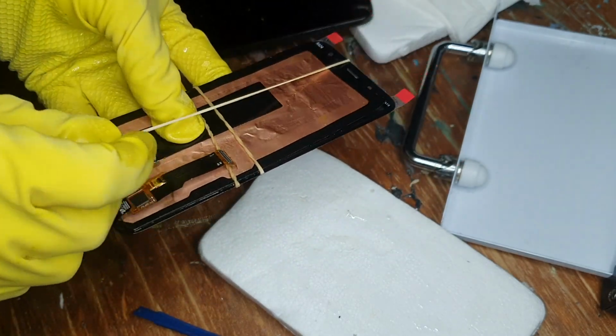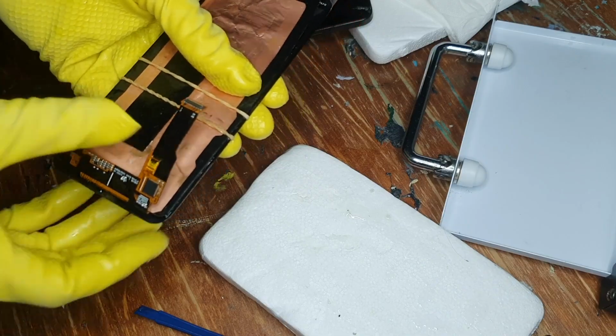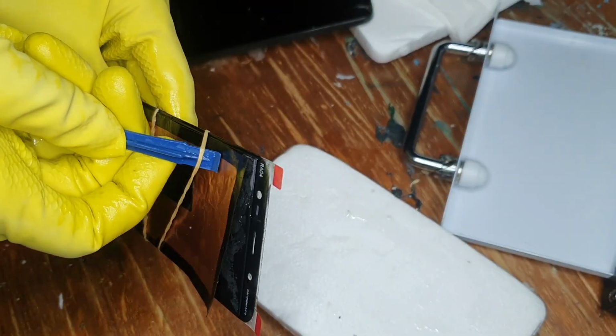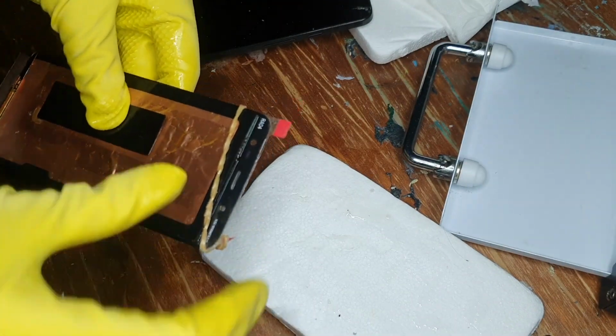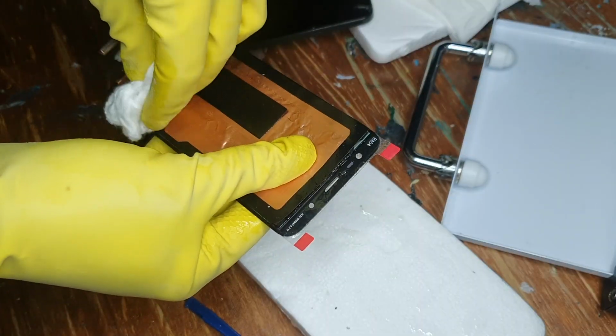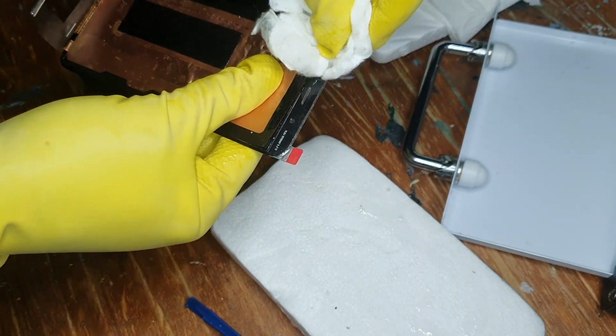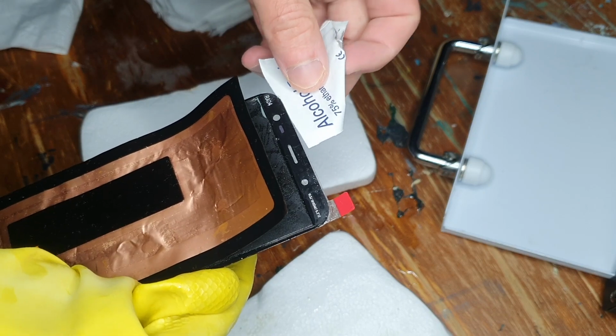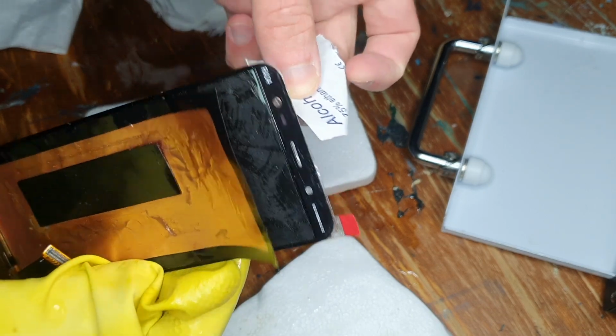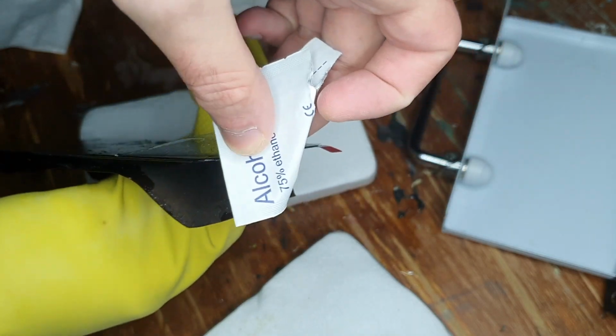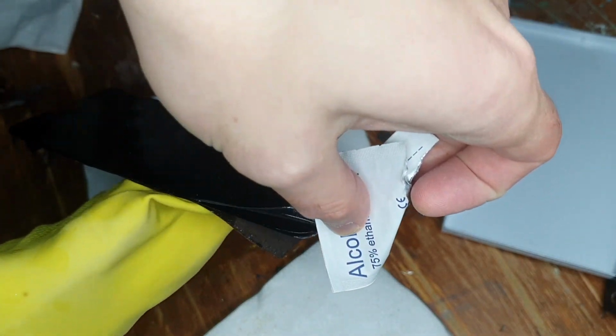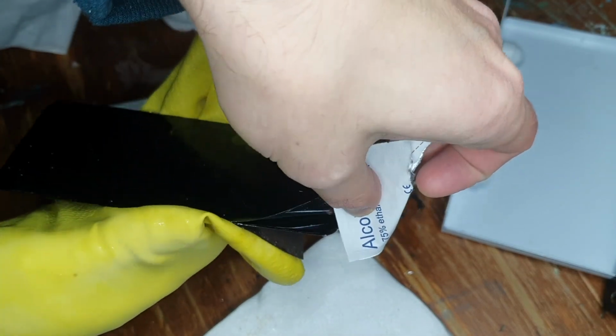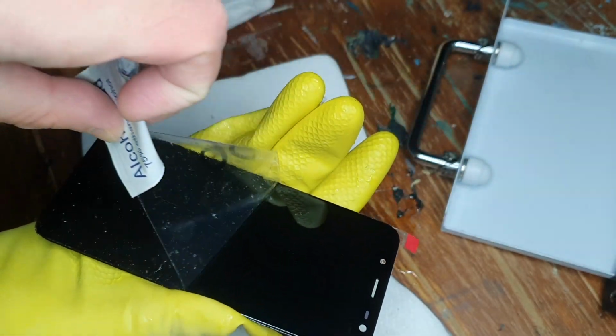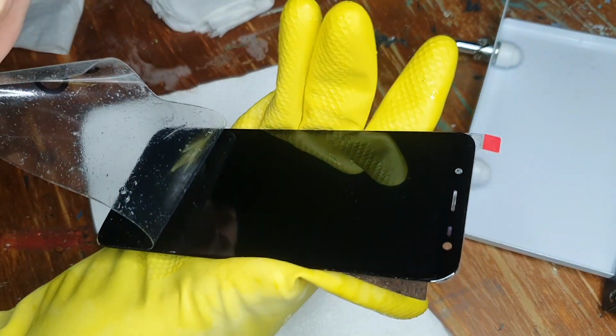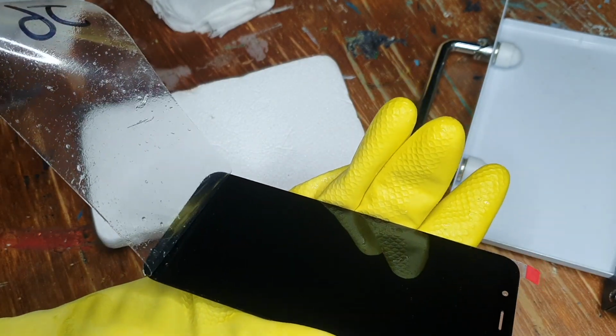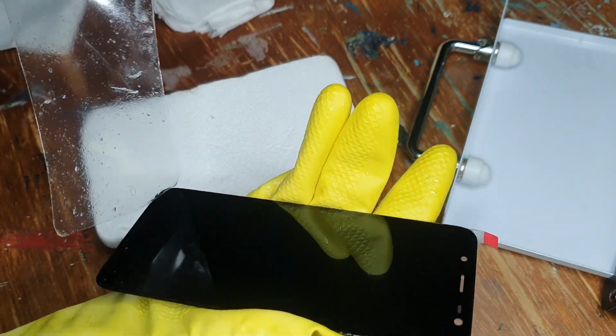So after half an hour in the UV light, it's time to take the rubber bands off and see if the screen is properly attached to the glass. And yeah, it looks like the glue has properly attached the glass to the screen and there are no air bubbles really. However, at this point I realized one thing I should have realized way sooner, and that is that some LOCA glue types are actually conductive.